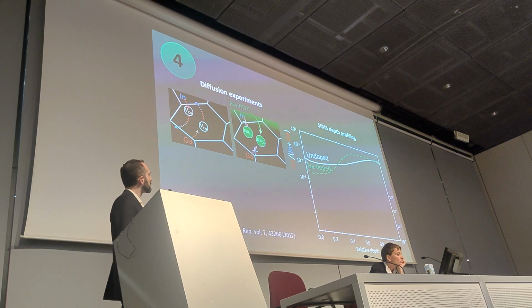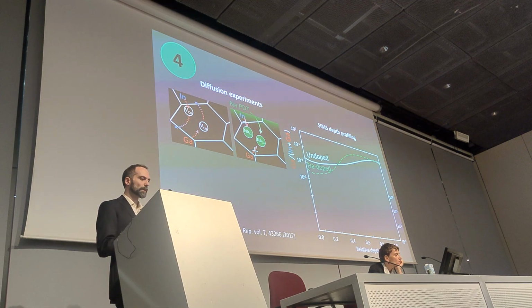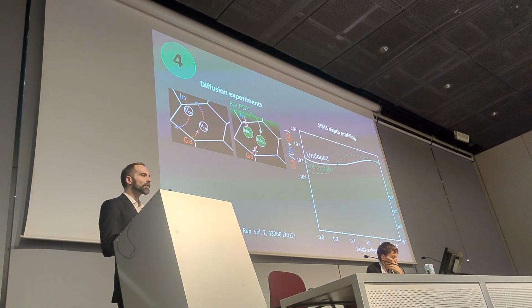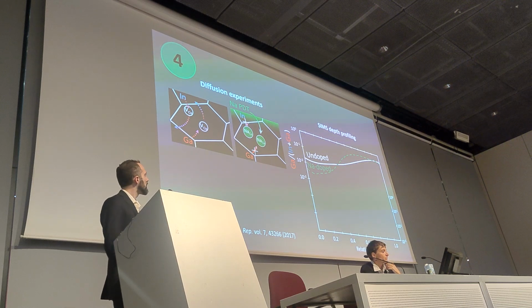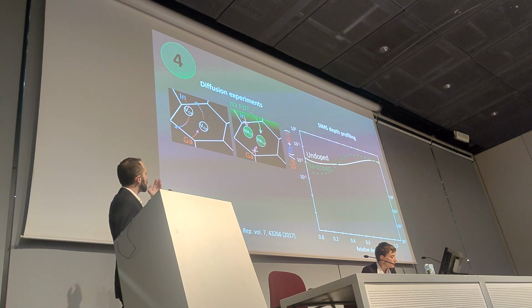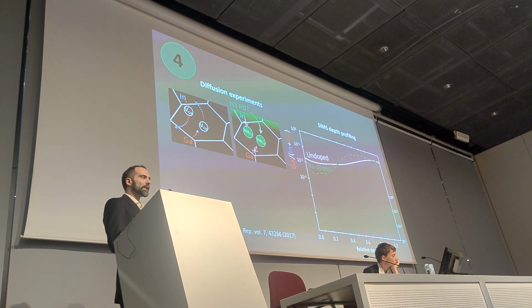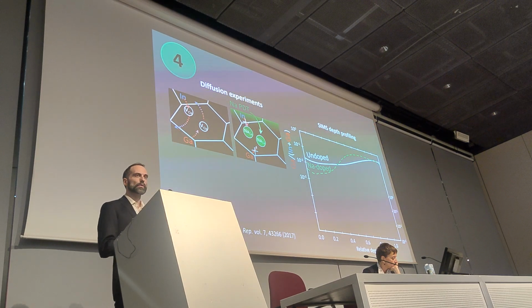What happens now if I add sodium to the system? We get a steeper gradient of gallium distribution. This is known for 20 years, and the community actually came up with a satisfactory explanation as to why this is the case, because diffusion of indium and gallium goes through copper vacancies, and presumably what sodium does when it gets incorporated, it forms sodium on copper, so it basically clogs the vacancies, so you have less possibility for indium and gallium to diffuse. Fair enough.